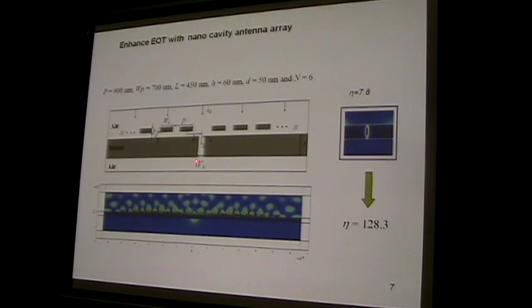You can think about this structure as a nano detector. This is a light-harvesting structure, and here you just put in a nano detector, for example indium phosphide at the near infrared, with a quantum well structure. Then the very large area of light will be collected, harvested, and squeezed to the single hole, reach the nano detector region, and be converted to an electrical signal.